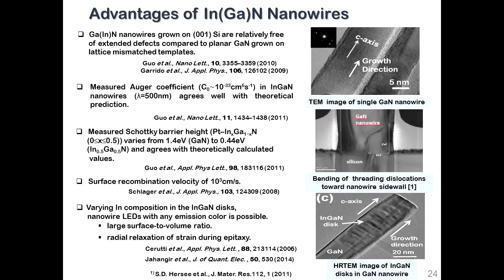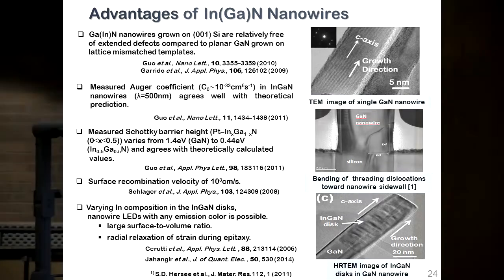So what are the advantages of these nanowires? They have a large surface to volume ratio, so the defect density is low. In fact, this is the purest, the most defect-free form of the nitrides that one can get. And that's one thing that got me interested, that you can do not only good material science with this, but you can probably think of devices that one has never thought of. The other advantage is that as they grow, there is a radial relaxation of strain, and so the polarization fields are small. That's the other big advantage.